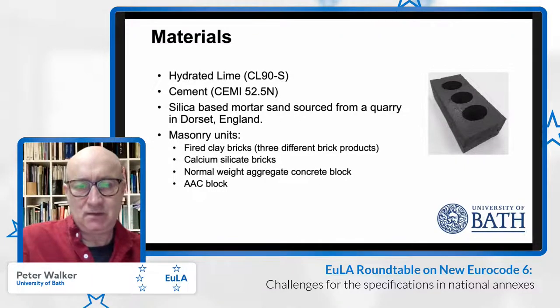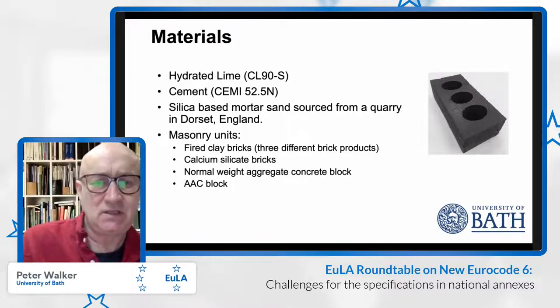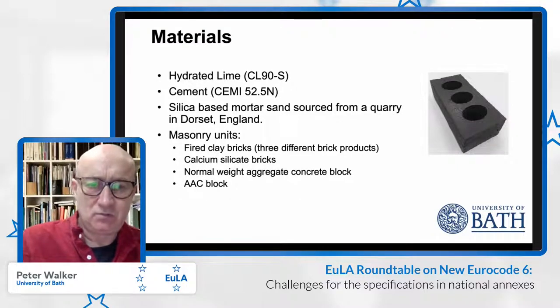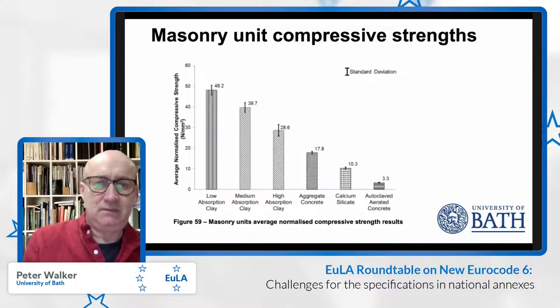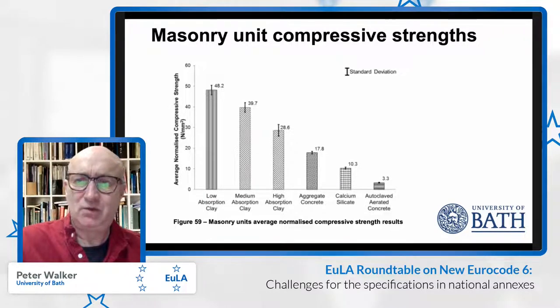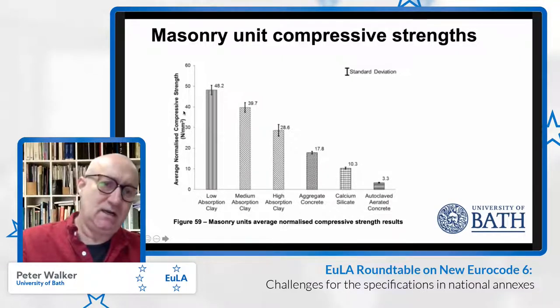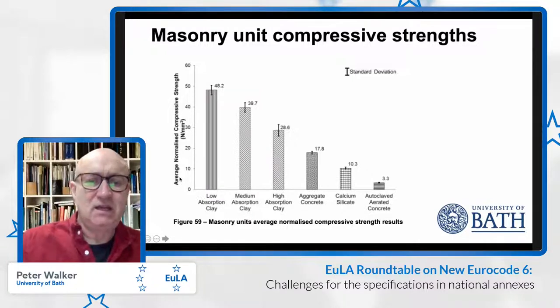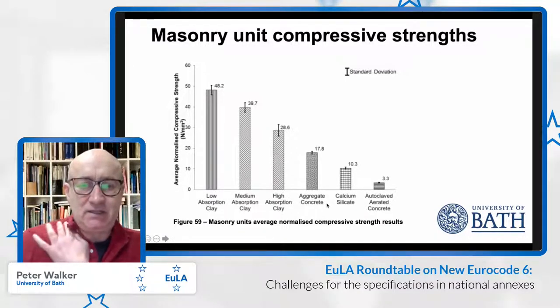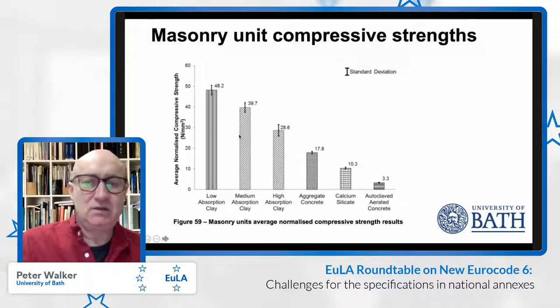We also extended to look at one set of calcium silicate bricks. These are not widely used in the UK, but recognizing that they are more widely used in other European countries. And then we also looked at a normal weight aggregate concrete block and an autoclaved aerated concrete, lightweight concrete block as well. So in terms of, just to give context, the masonry unit properties here, first of all, the compressive strengths, and these are the normalized strengths in terms of a standard, and they're presented here in decreasing strengths and classified in terms of the water absorption properties of the clay bricks, and then the concrete, the calcium silicate, and the AAC block at the end. So you can see the range in strengths between 48.2 for the highest strength clay brick down to 3.3 newton per square millimeter for the AAC block.